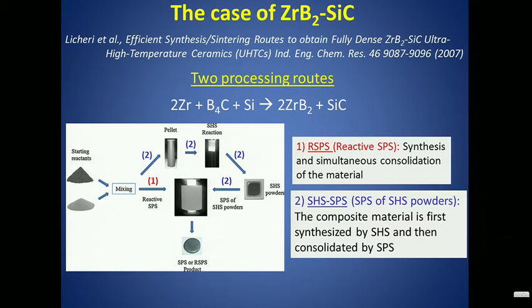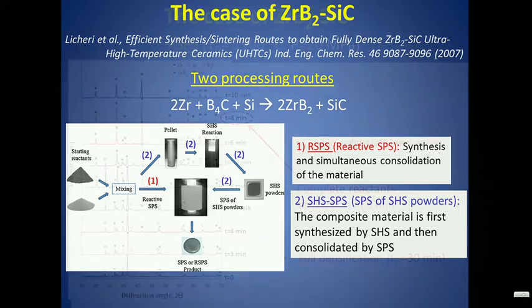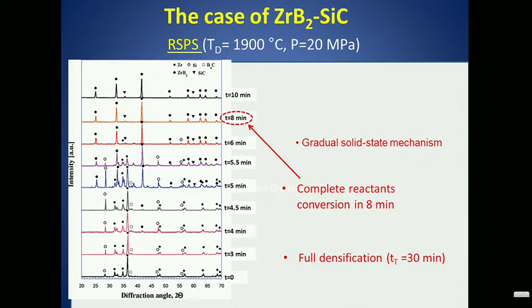Let us see how to compare these two processing routes. The first one is the reactive SPS. What you can see is that in just 8 minutes, through a gradual solid state mechanism, you get complete reactants conversion. This is the total time. Of course, that is the conversion in 8 minutes. But out of it, 30 minutes is the entire time to get the complete reaction and the densification of the